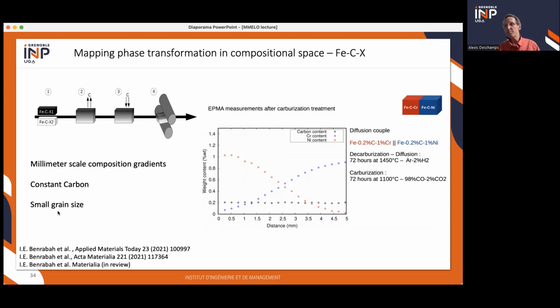The small grain size is particularly important because it's difficult to get good diffraction conditions. If you want to get quantitative data, really to have powder conditions is absolutely necessary and quite difficult to reach. So it's a very important point. So here is the kind of composition profiles we get. Here it was joining two alloys, one with chromium, one with nickel, and you get an interdiffusion composition profile over here, 5 millimeters, and constant carbon. So then you have a whole set of different steels that you can probe by moving through this composition gradient.